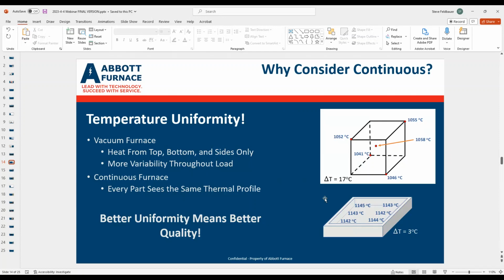Likewise, in a continuous, when we instrument this and we measure it, we're seeing about as little as a 3 degree C variation. Typically, it's somewhere under about 5 degrees C variation around through the boat. The reason is every part in that boat sees the same thermal cycle. Each one is exposed to the heating elements the same as the part next to it. So the thermal history of that part is very uniform. And the advantage to this thermal uniformity is when you have better uniformity, you have better quality because you have better consistency. Your variability goes down. That translates into a better quality product being delivered to the customer.